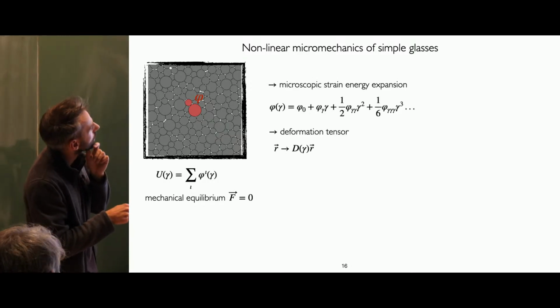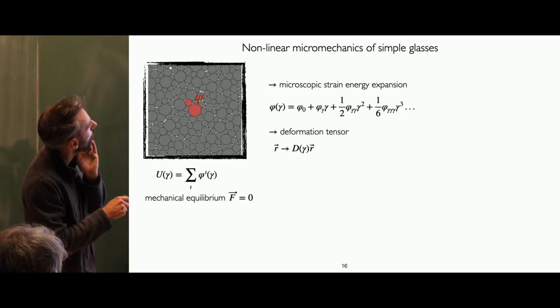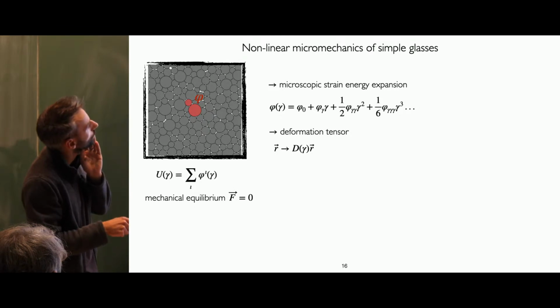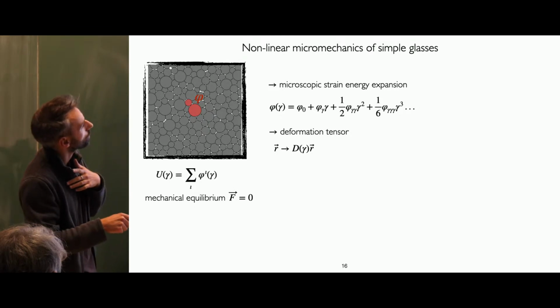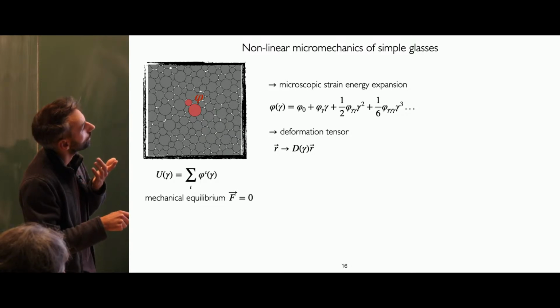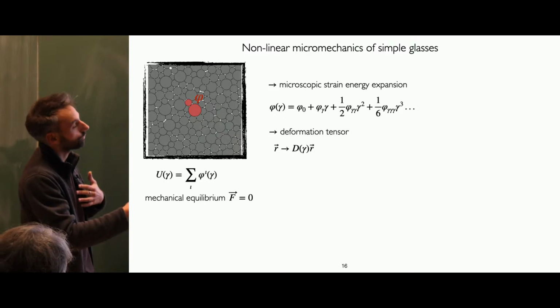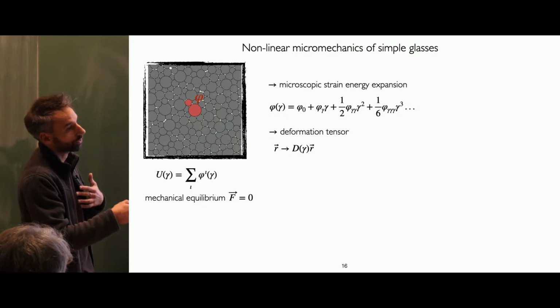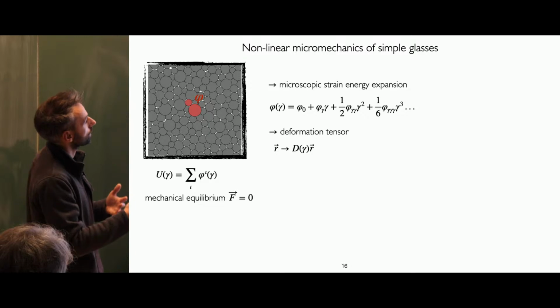And what we recently succeeded to work out is that, at the level of bonds, we could work out a nonlinear strain energy expansion for a given deformation tensor. So now I don't only know the potential energy, but I know how it is going to change at some orders in strain if I start to deform my system with a given deformation tensor. So you can do this kind of trick.